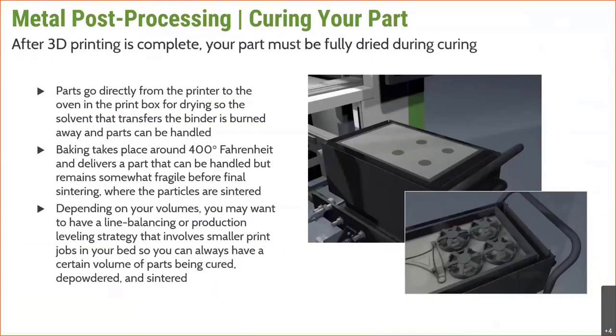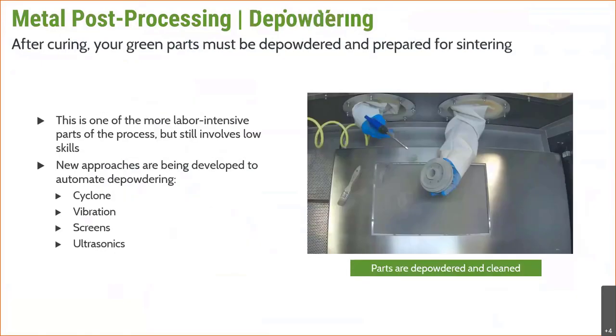So the curing of the part goes into an oven. It's going to be raised to about 400 degrees F. That's done to drive off the water or aqueous solution in the aqueous part of the binder and cross-link some of the polymer. Depending on part thickness, build size, and build box depth, those can range in different hours, but it's part of the whole process. The next part of the process is the depowdering.